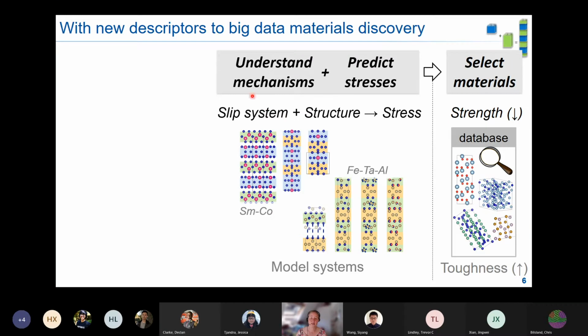And for that, we need to understand the mechanism so that we can then predict stresses based on the crystal structure. And there are difficulties, and the main one is that actually you have to know the slip system to do the analysis I just showed you. If you want to measure the distance between two slip planes, you have to know which plane that is, and you have to know which Burgers vector a dislocation might have. And that's something that for most intermetallics, for example, we simply don't know.